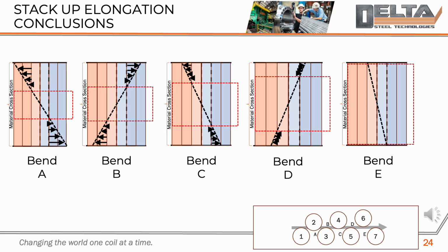Then, as the material moves through each subsequent roll, these forces reverse. What was in compression now goes into tension, and vice versa. With each reversal, the magnitude of deformation decreases, and you can observe how the neutral region in the center gradually grows larger. As we move forward, we'll examine how different variables affect this pattern. We'll see how adjusting the roll penetration impacts material behavior, how the number of rolls in a leveler affects our results, and how different material properties, particularly yield strength, change the way we approach the leveling process. Understanding these relationships is crucial for achieving optimal flatness in your steel processing.